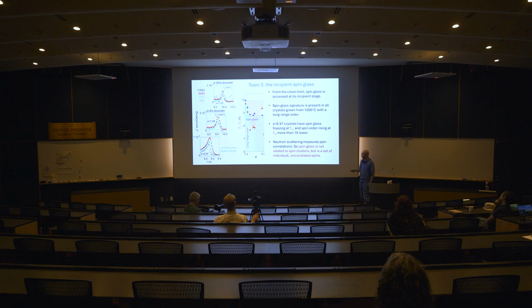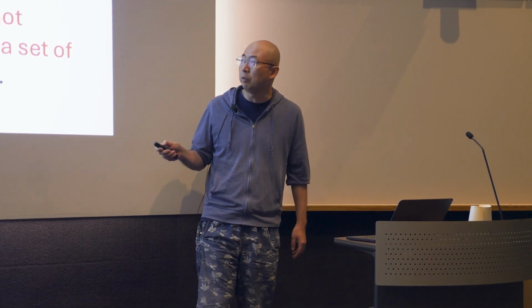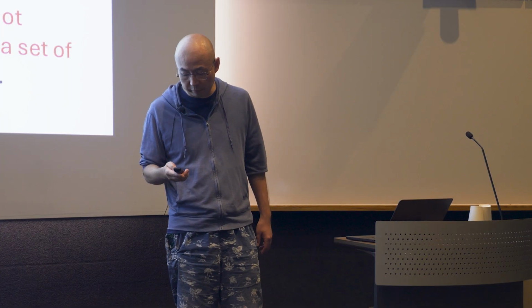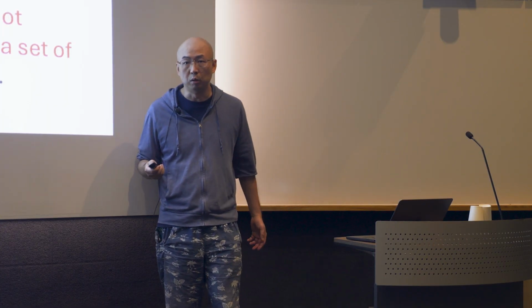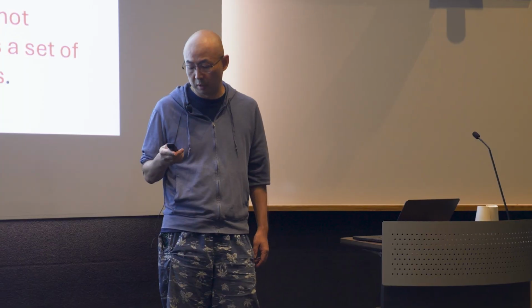And beyond that, in this 97% sample, the spin glass freezing temperature happens about 1.2 Kelvin above where the long-range order develops. So whatever the spins freezing here has nothing to do with long-range order developing. With that, you can conclude spin glass is not related to spin clusters at all. It's only the individual uncorrelated spins in the sample because you dope the disorder into it. I mean, it's sort of an anticlimax, but you have to have an experimental narrative to prove that. And that's our proof.